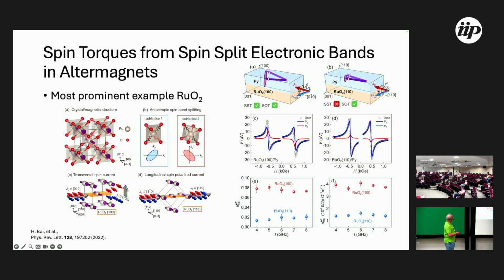And so what they did is they made samples with different orientations of ruthenium oxide, and indeed they see that they get large spin torques, indicative of large spin accumulations in the ruthenium oxide for one orientation and negligibly small ones for the other one. And so they suggest that is directly related to this altermagnetic band structure, where you have spin splitting in one direction but not in the other.